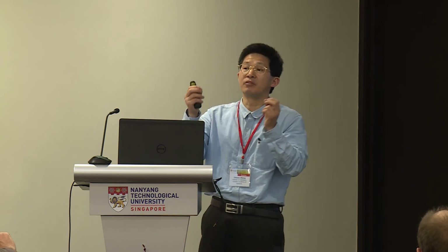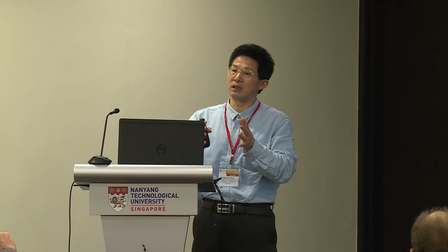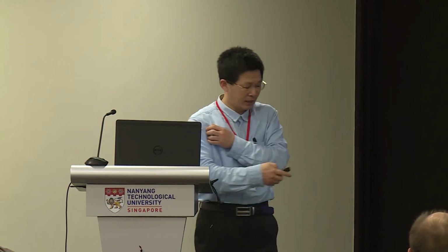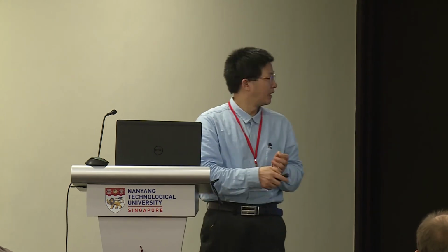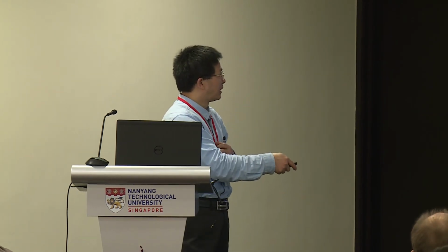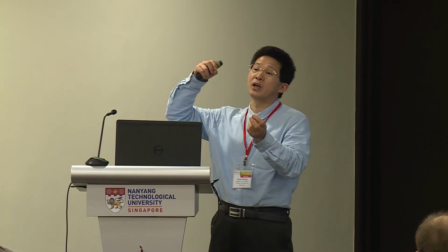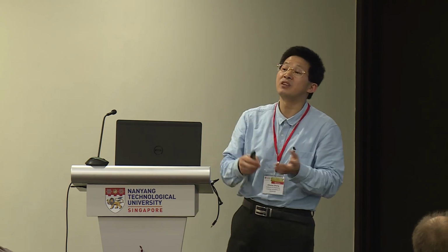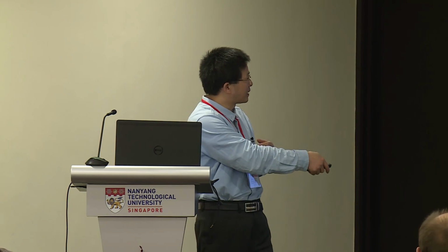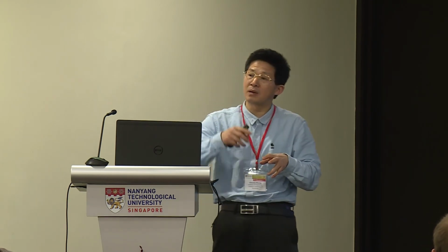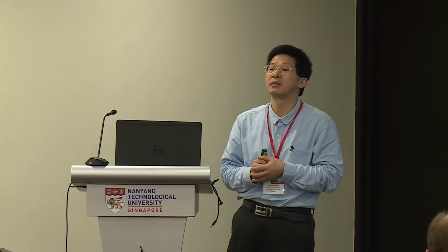So this is the first thing. If another compound formed, you would see activity after some time, but here you only see it at the beginning. The strontium sample can actually survive for several days. We put the crystal in the solution with water, and we see the oxygen come out immediately. This is measured by a Clark-type oxygen measurement.